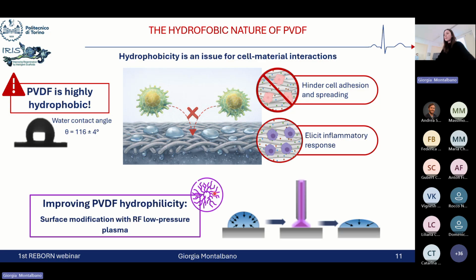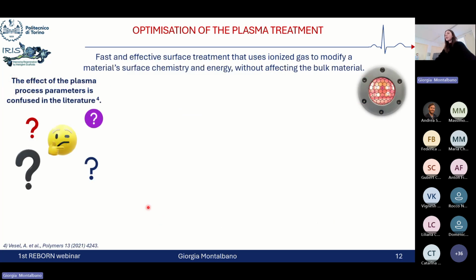So we tried to explore the possibility to improve the PVDF surface hydrophilicity of our patches by exploiting a fast and effective surface modification using radiofrequency low pressure plasma. So the choice of this surface treatment was based on the fact that plasma treatment can be very fast and effective in the variation of the material surface chemistry and energy, by exploiting ionized gases without affecting the bulk material.